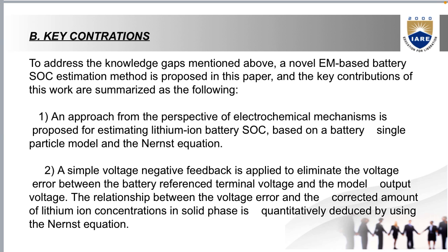Number 2. A simple voltage negative feedback is applied to eliminate the voltage error between the battery reference terminal voltage and the model output voltage. The relationship between the voltage error and the corrected amount of lithium ion concentrations in solid phase is quantitatively deduced by using the Nernst equation.